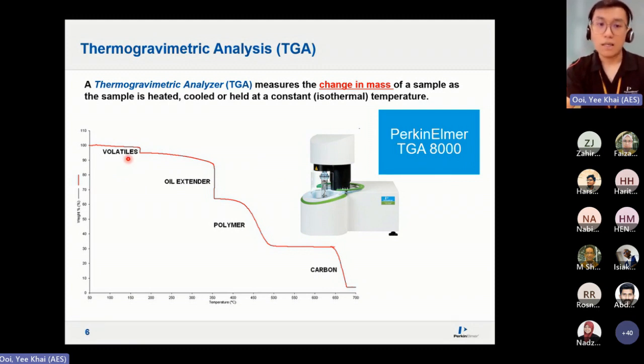Hence, usually less than 200, what you are going to get is usually your volatiles, whether it's oil, moisture, or residual solvent. So some people use TGA to do residual solvent analysis as well. Usually you do need a sensitive balance to read that if that's the case. Hence TGA 8000 with a 0.1 microgram ultra micro balance.